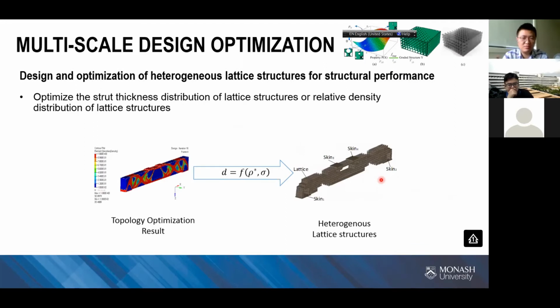Another thing that I mentioned before is that we also do some research on how to design heterogeneous lattice structures with functional gradient property distributions. So for example, we have a property distribution like this, and we can map it to meso-scale or micro-scale structures. We can have functionally graded materials. We use topology optimization with a defined function mapping from the topology optimization result to the lattice result. So it can help us to further improve the structure performance. This is about structure performance.